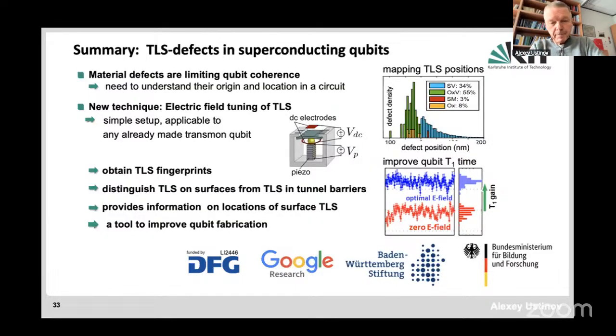So I told you some of our recent studies about two-level system defects in superconducting qubits. They are limiting the qubit coherence. They are the main obstacle now for moving towards scalable fault-tolerant quantum computers, because one needs to achieve significantly higher quality of superconducting circuits to achieve high coherence. We have developed different techniques, both strain and electric field tuning of frequencies of qubits. By measuring the fingerprints of those TLSs as a function of either strain or electric field, we also can learn about the physical properties. We can distinguish between TLSs and the interfaces.